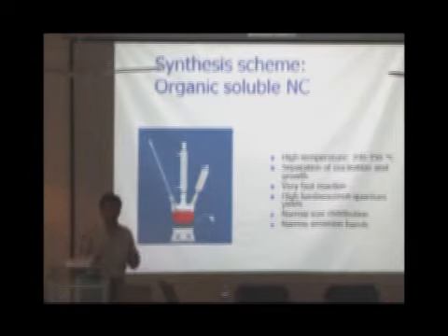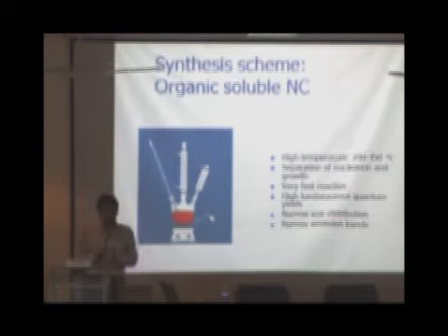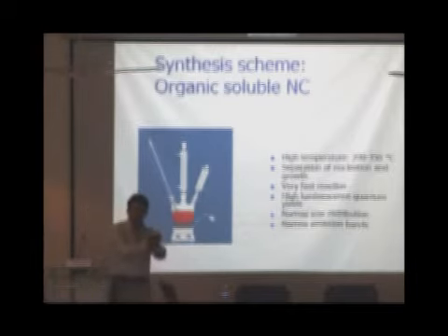Now, the main aim is to make high fluorescence particles, and since we're going to make some studies for applications, I don't think people are going to bother too much if there's a huge distribution. So what you want is a narrow emission spectral feature, and for that, a very narrow size distribution. Some methods like microwave synthesis or solvothermal synthesis give you a rather broad size distribution. But this particular scheme, where you can separate nucleation and growth, means you have the atoms, and you first form nuclei on which more and more atoms get deposited to form the particles.